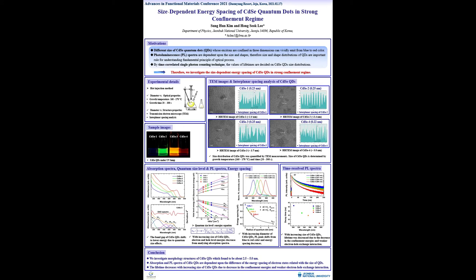By using differential absorption spectra, we can fit Gaussian peaks by the original absorption spectra. Each Gaussian peak shows distribution by exciton transition. Also, each peak energy of the Gaussian peak corresponds to electron transition energy, which is followed by the selection rules for orbital transitions.